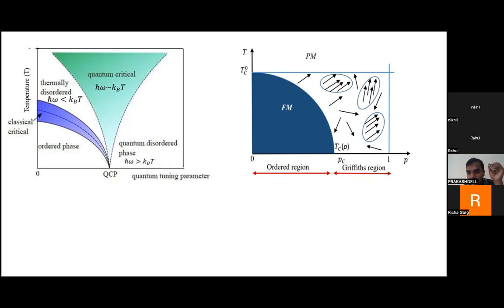In any conventional magnetic phase transition, the magnetization at T_C doesn't fall like a step function. There is a broad transition, and the magnetization doesn't sharply touch the temperature axis; it approaches it asymptotically, and that is known as the tailing region.